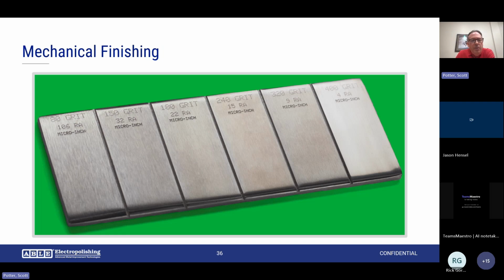A lot of people are familiar with grit callouts. Here, for mechanical finishing purposes, if somebody mechanically polished a part before electropolishing, it gives you a relationship of grit and Ra. You can see you're starting out at a rougher grit, 80 grit, going all the way down to 400 grit. You can see what the relative Ra levels are for the different grits.